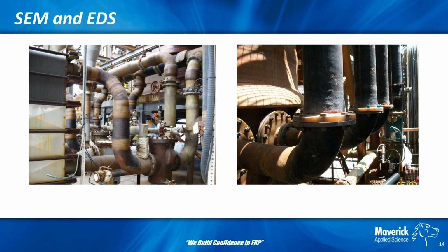So we've talked about SEM, we've talked about EDS. These are very quantitative measurements for this. One thing that was kind of interesting from all this: you can see all the discoloration and some of it looks pretty bad. And going into this, we expected that was going to be sulfur. You've seen sulfur when it's burnt like this, it kind of gives you that brown tone. And when we actually did the elemental breakdown, we found that what was on the surface was not sulfur, but in actuality it was iron, and that had actually migrated to the surface, obviously through some of these conduits that the glass afforded for it later on.